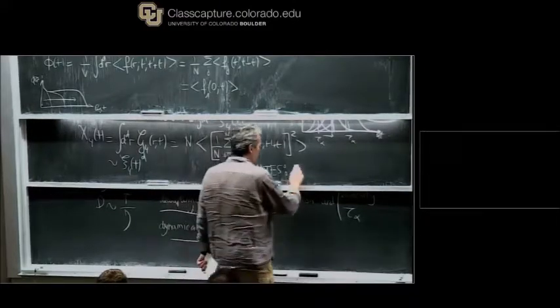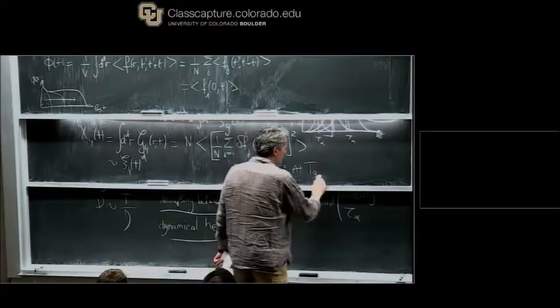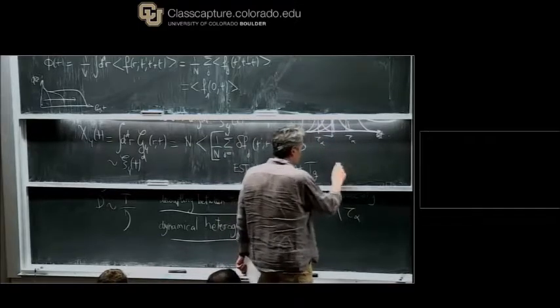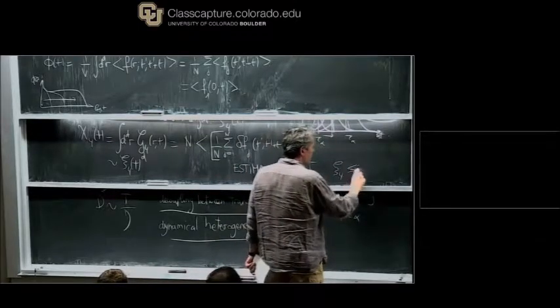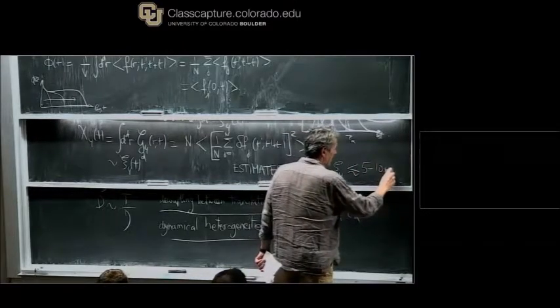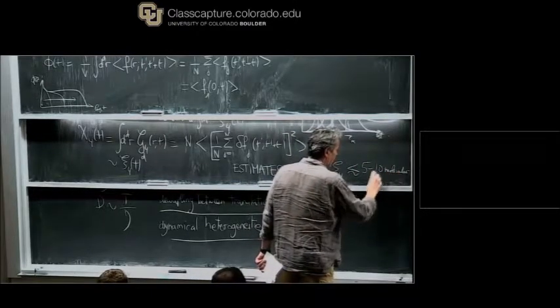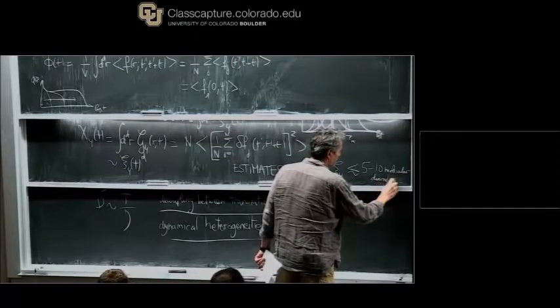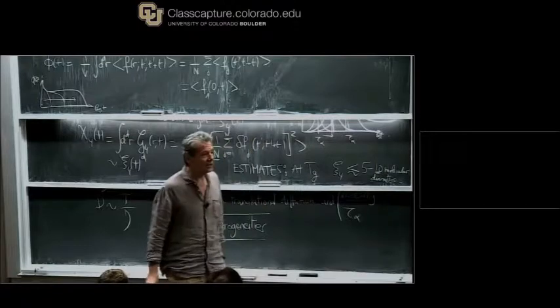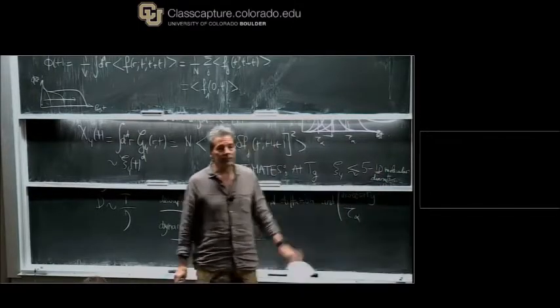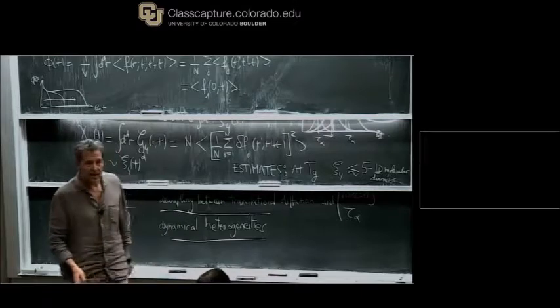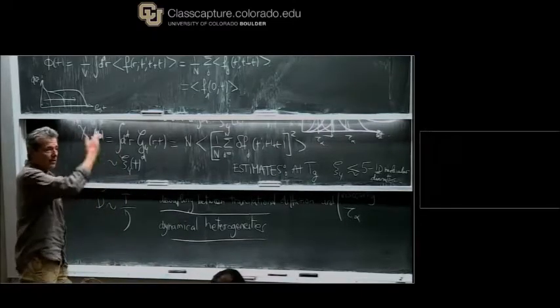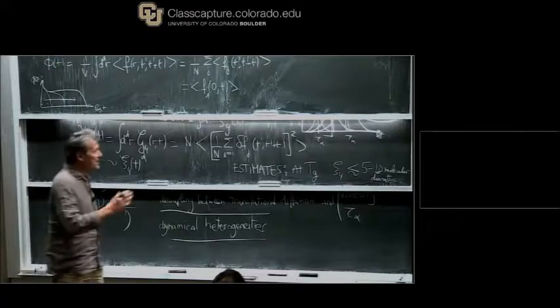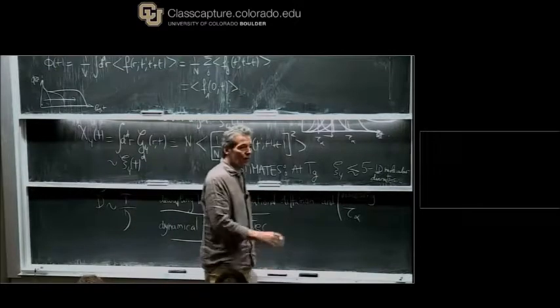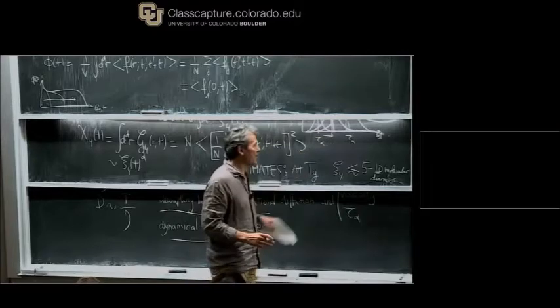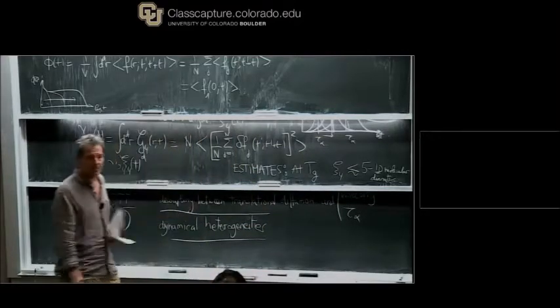When you lower the temperature, basically at Tg, the estimates are that the length scale, let's call it Xi4, is of the order of 5 to 10 molecular diameters. And 10 is very optimistic. So this is to give an order of magnitude of the kind of length scale that we encounter in glass formation. In simulations, you can measure it over a shorter time range, and it increases by a factor of 5 to 6 or something like this.